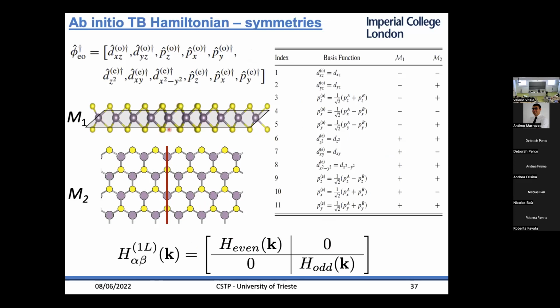So basically, there are these 2 mirror symmetries. One is this in-plane mirror symmetry, M1, and the other one is this M2. The d orbitals are all symmetric with respect to M1. So you can already classify the d orbitals into even and odd with respect to this M1, but you can further classify them in terms of this M2 symmetry. And you can create combinations of p orbitals that are even or odd with respect to these 2 symmetries. The reason for doing that is that you can separate the Hamiltonian and make it more sparse, and you already build in the symmetries of the system in the Hamiltonian.